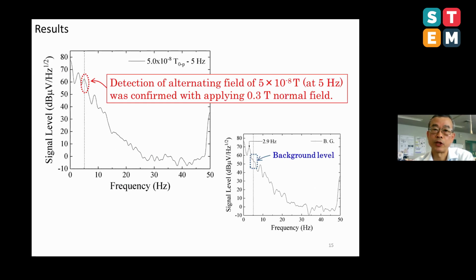When the applied field decreases to 5 × 10^-8 Tesla, the measured spectrum changes as in this sheet. We can see that the 5 Hz peak of the signal distinctively sticks out from the background level. As a result, our thin film sensing system can detect a signal seven digits lower within the 0.3 Tesla static normal field.